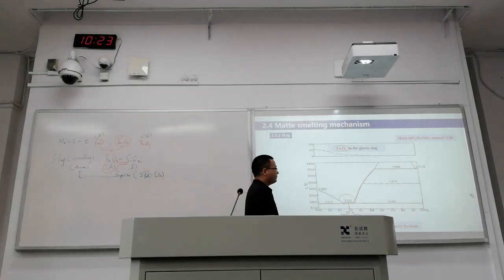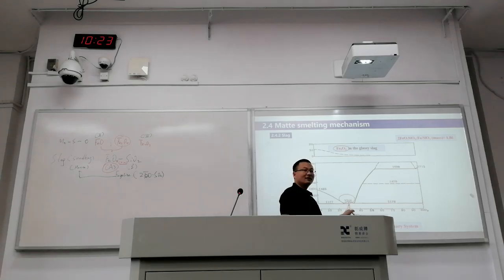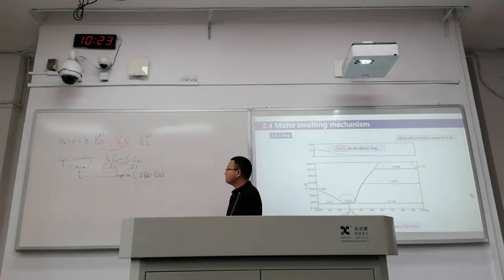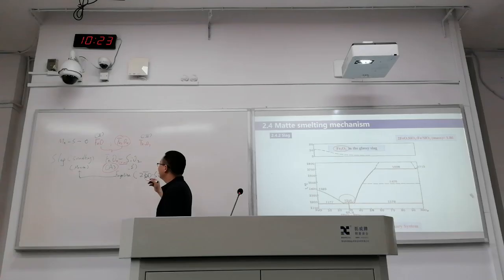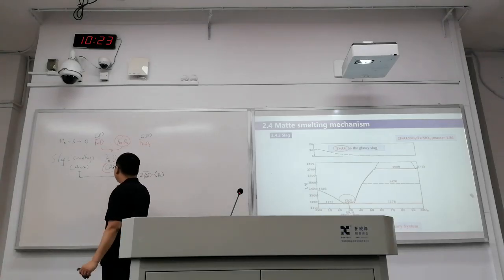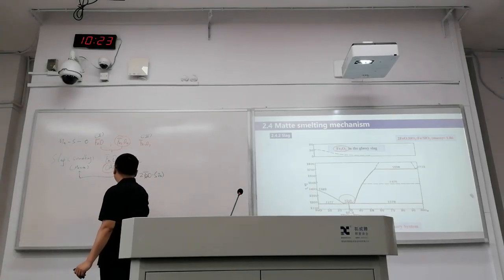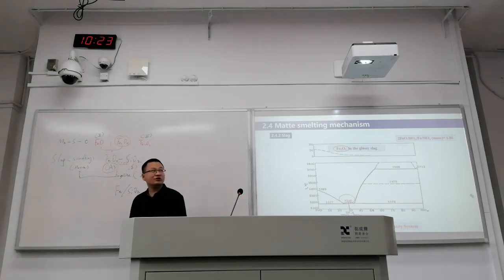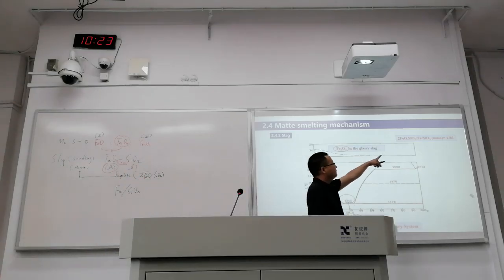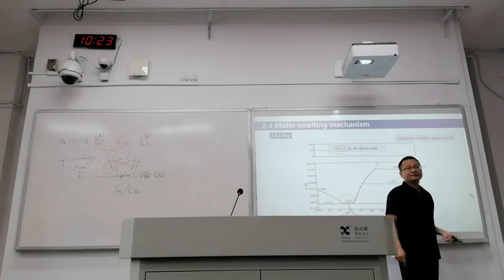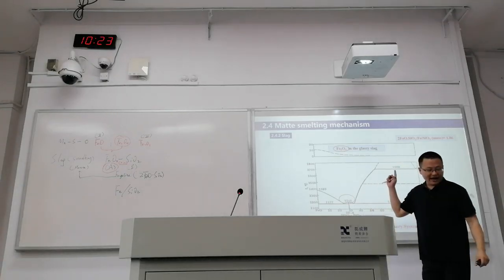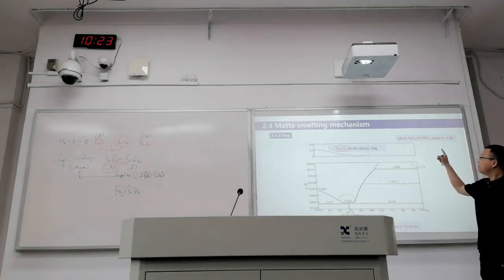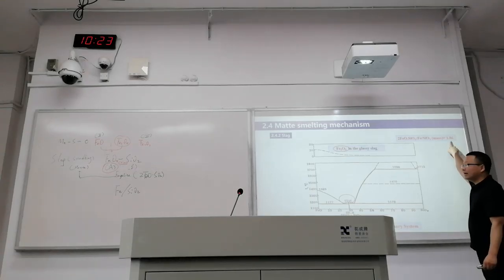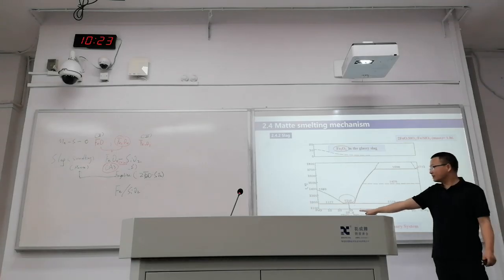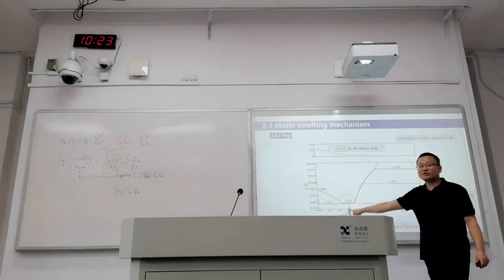But the interesting part is, when we are talking about slag, the most important indicator will be the iron silicon ratio. I will put it here. Iron silicon ratio: the percentage of elemental iron and the percentage of silicon oxide in the slag. So this is 1.86. This is the one here.